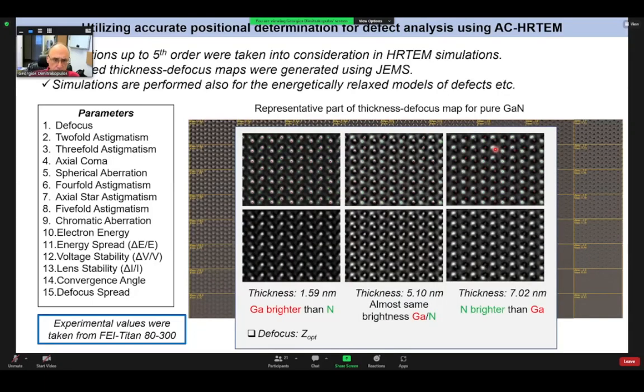In fact, first we have to do the hard work, which means that we have to do image simulations. In our community, if you want to do image simulations for transmission electron microscopy, not scanning transmission, just transmission electron microscopy, you use the JEMS software, and you can find with which conditions, for example, if you have a binary compound like gallium nitride, you can see the gallium columns brighter, or the nitrogen columns brighter, or both columns with about the same brightness.